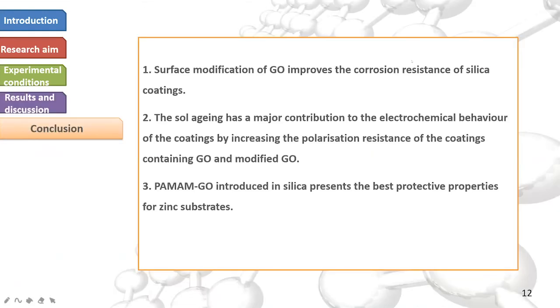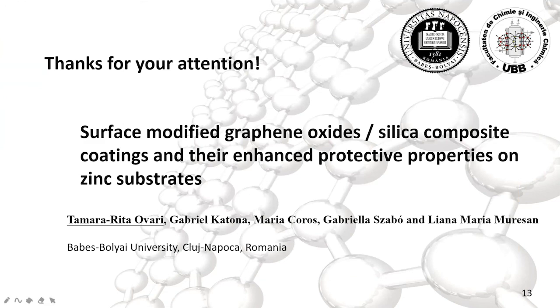And as the conclusion, the surface modification of GO improves the corrosion resistance of silica coatings. The soil aging has a major contribution to the electrochemical behavior of the coatings by increasing the polarization resistance of the coatings containing GO and modified GO. And PAMAM-GO introduced in silica presents the best protective properties for zinc substrates. And thanks for your attention.